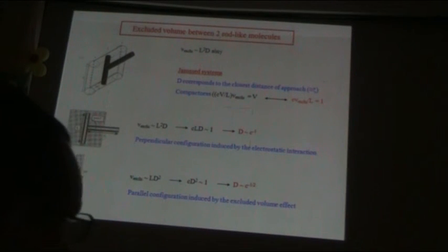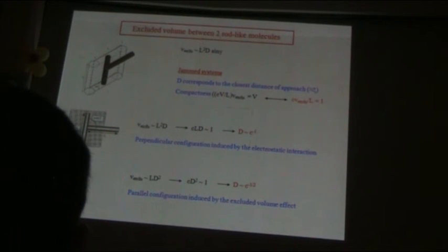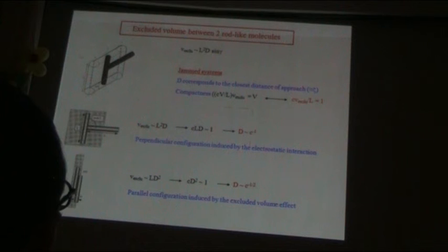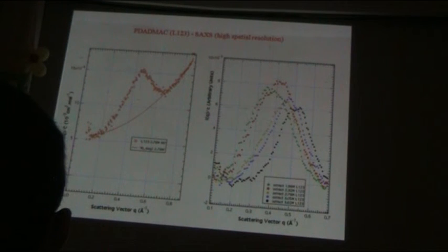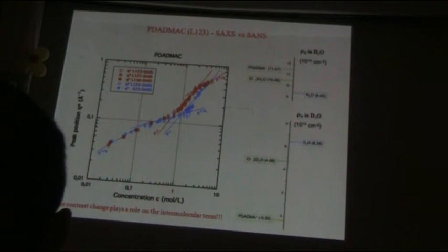When you increase the concentration, the electrostatic interaction decreases, of course, but you have this combination of the electrostatic interactions and the compactness argument. And that is why you observe this metastable regime in between the concentrated regime and the nematic phase. And you see, in this case, you don't observe any uniform approach. I finish in one minute, sorry.